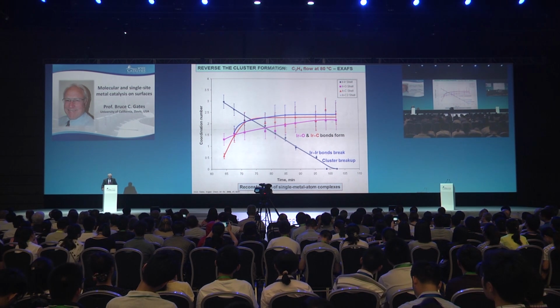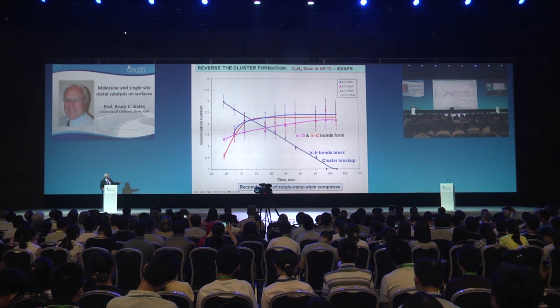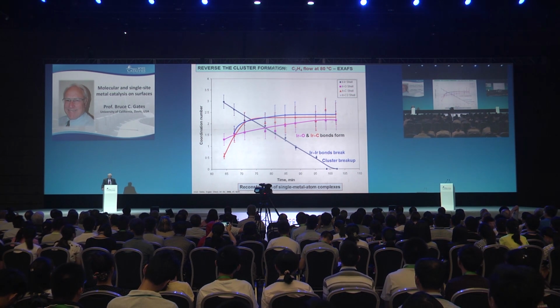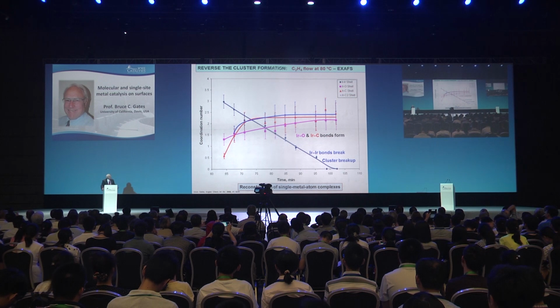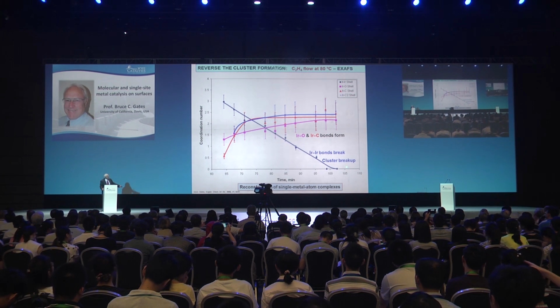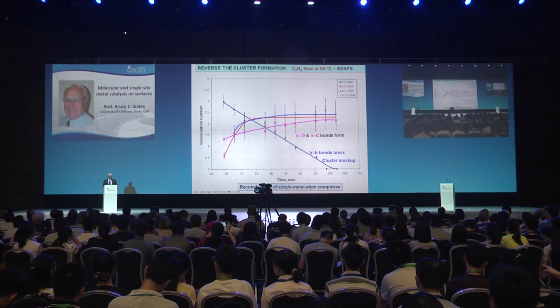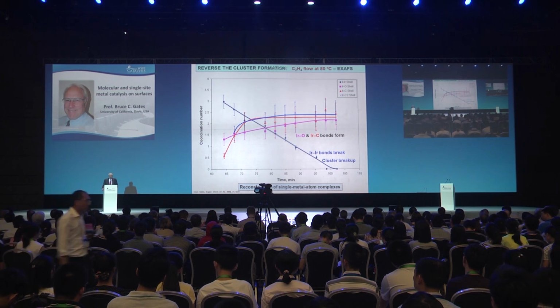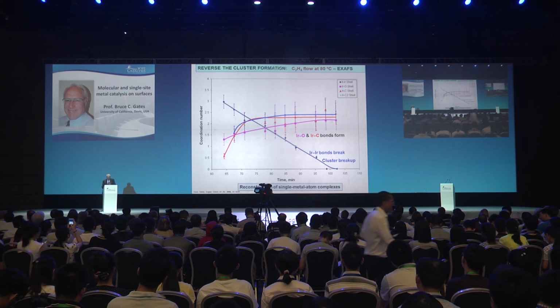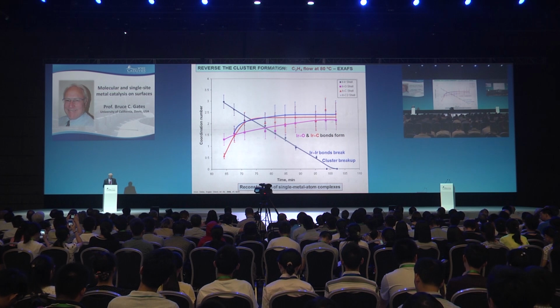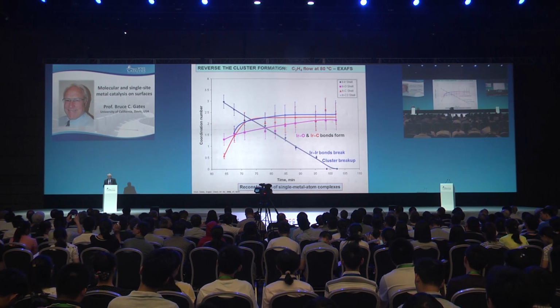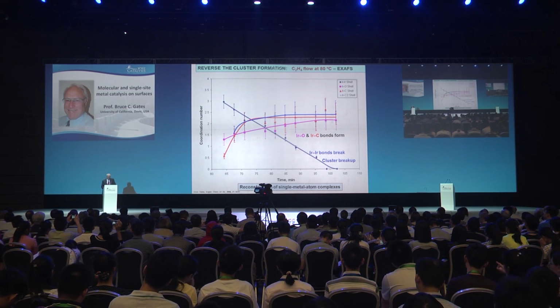So we can start with the cluster, treat it with an oxidizing agent, just ethylene, and that fragments the cluster, and we go back to the mononuclear complex. So nature was very kind in this case and provided a way to control the formation of clusters and complexes with high yields in the synthesis, and on more than one support.